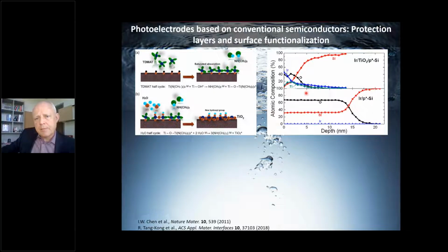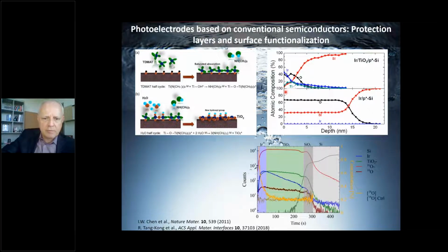So because of this chemisorption limited deposition mechanism, the ability to deposit dense and closed layers at small thickness, it's an interesting approach for making corrosion-resistant coatings. TiO2 is one of the oxides that is stable according to Gerischer's rules for stability under water oxidation conditions, and we see for the TiO2 coated silicon sample shown here after many hours of testing that the structure of layers, an iridium oxide OER catalyst, TiO2 protection layer, and the silicon substrate remains intact in this depth profile. But if the TiO2 is left out of the stack, we see a very significant oxidation of the surface of the silicon, and the iridium-based catalyst is actually exfoliated from the surface as a result of the growth of the oxide and the stresses that form.